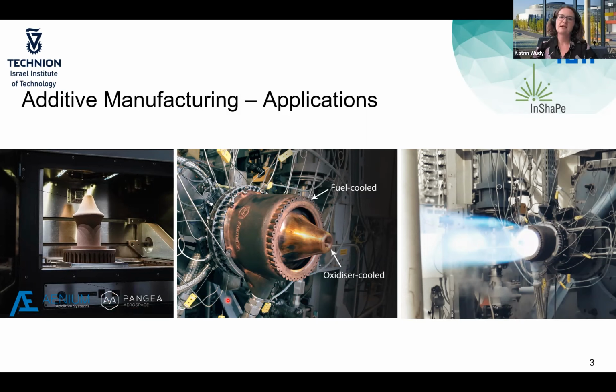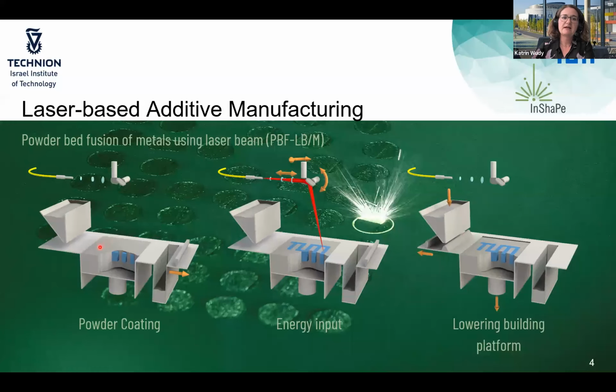And I would like now to focus on the process. So what are the process steps and what are the challenges in laser-based additive manufacturing, or rather powder bed fusion of metals using laser beam. On this slide, if you don't know the process and are not familiar with it, I just described it shortly. So powder bed fusion, I mentioned it, is one additive manufacturing technology where you have a powder bed. This is schematically shown here. The size of these powder particles is really small, around 50 microns, so the thickness of one of your hairs. And you have an energy source. The energy source here would be a laser system. It's a movable energy source with a scanning system, which is schematically shown here.